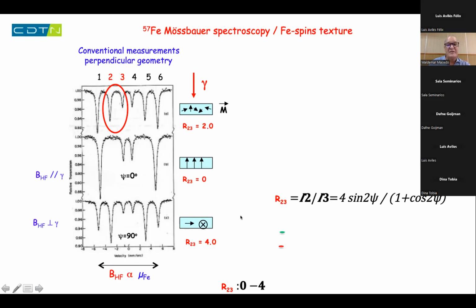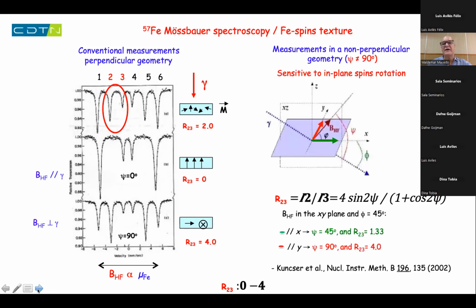But in this case, you are not sensitive to the spins in one direction or in the perpendicular direction. But if you can go to, let's say, a non-perpendicular geometry of the incidence of the gamma rays, in this case you are sensitive to rotation of the iron spins in the sample plane, okay? And this is what is important for the things I will show you today.